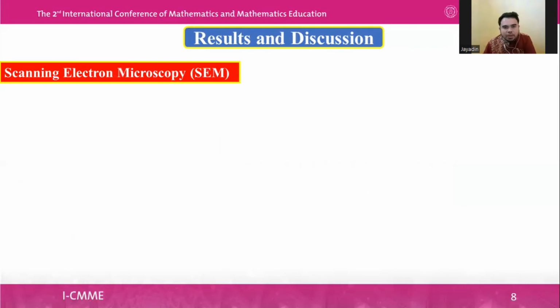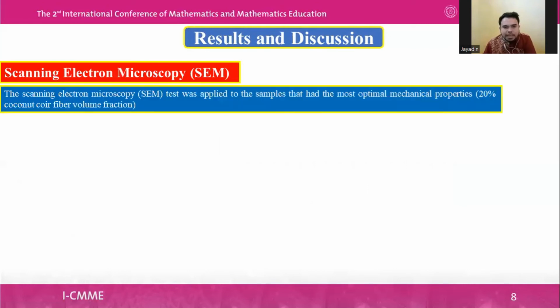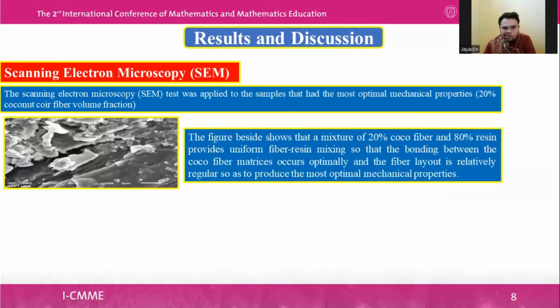Scanning electron microscopy. The scanning electron microscopy test was applied to the samples that had the most optimal mechanical properties. The figure beside shows that a mixture of 20% coconut fiber and 80% resin provides uniform fiber-resin mixing, so that the bonding between the coconut fiber and matrices occurs optimally and the fiber layout is relatively regular, so as to produce the most optimal mechanical properties.